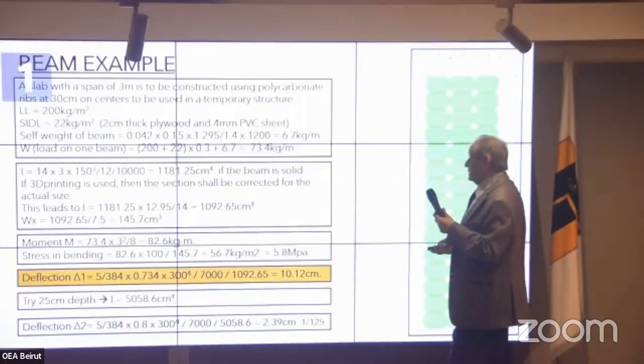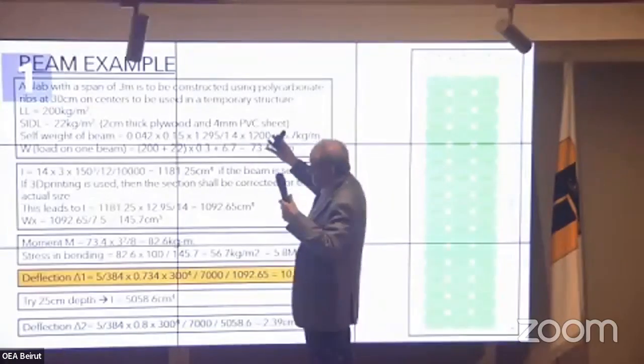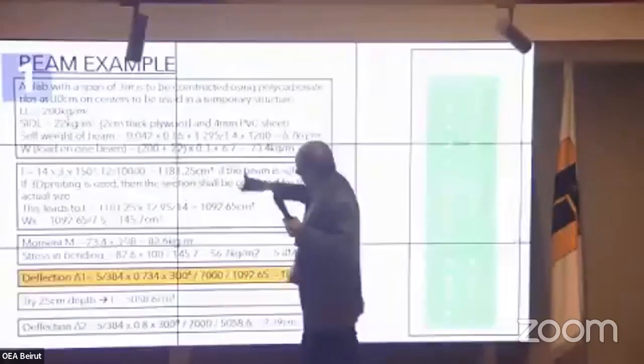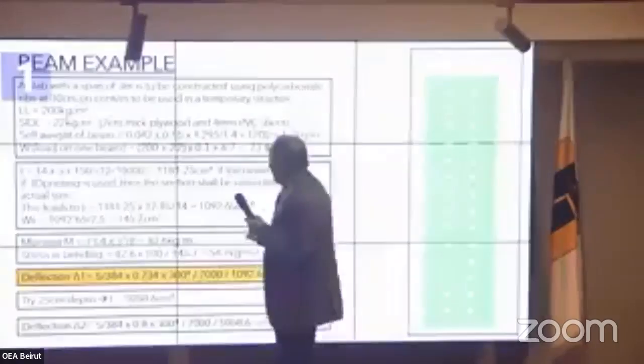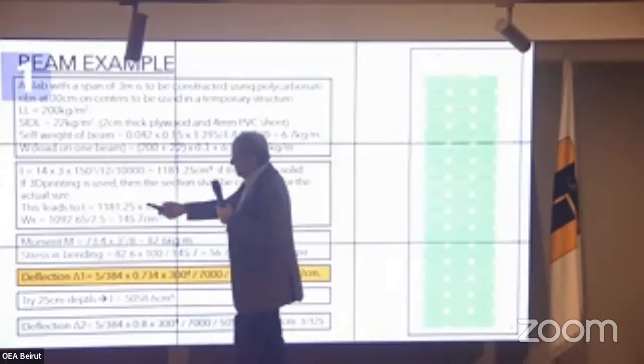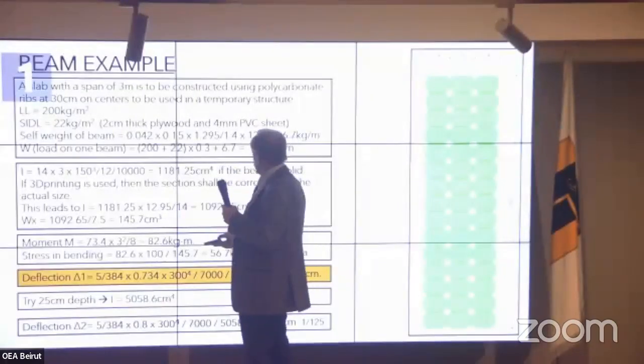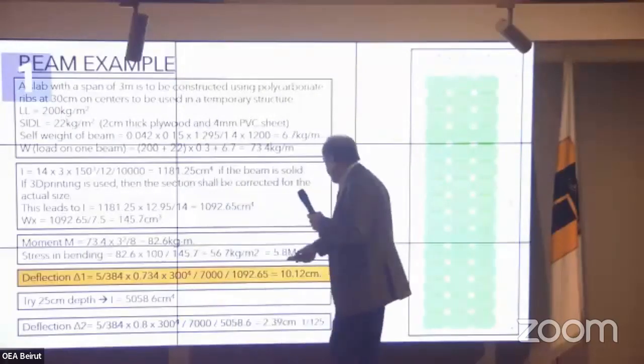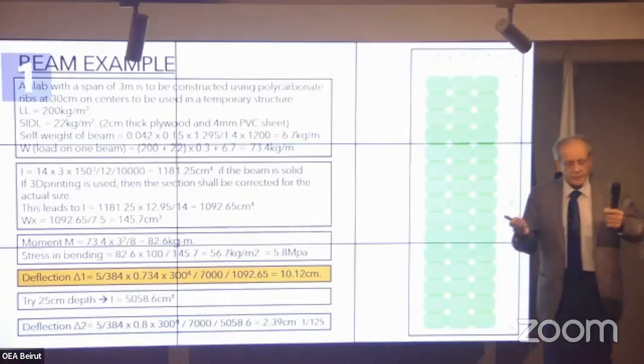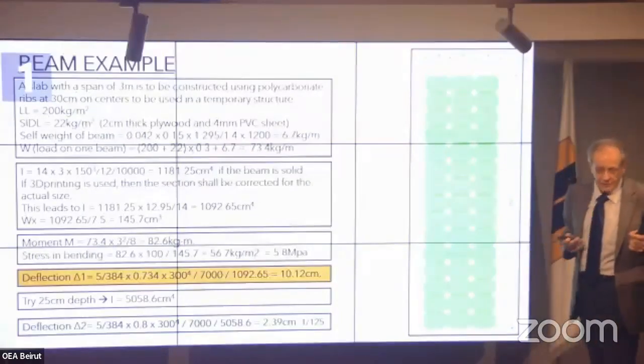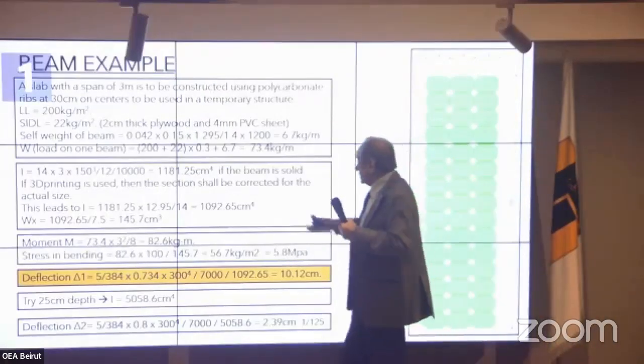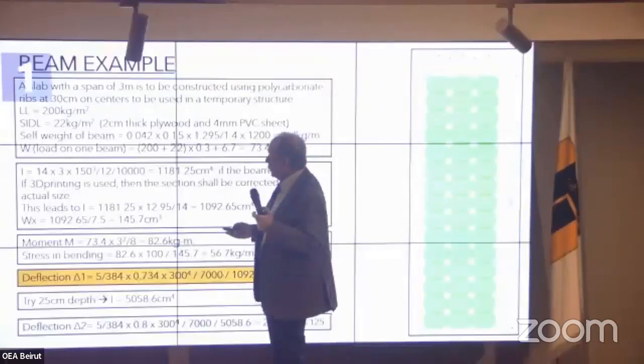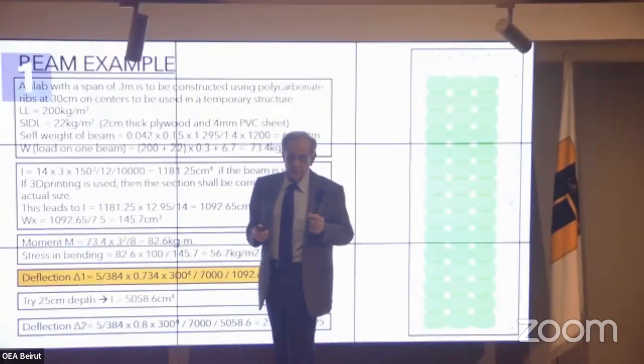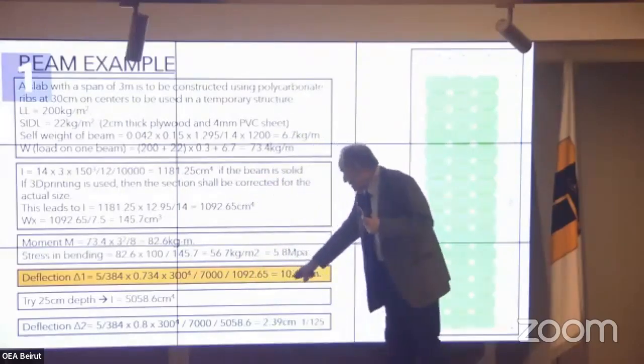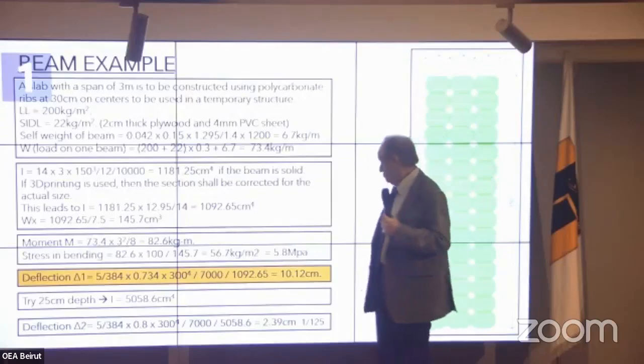I found that the problem is that, you can go through the calculations. I think I have to go through the calculations, but the problem is not the strength. The section modulus was 145.7 centimeter cube, and the stress was something like 5.8 megapascal, while the yield strength of this plastic is much higher than that, about 10 times that. So still, it didn't work. Why? Because of the deflection. Not any other reason. The deflection was 10.12 centimeters.